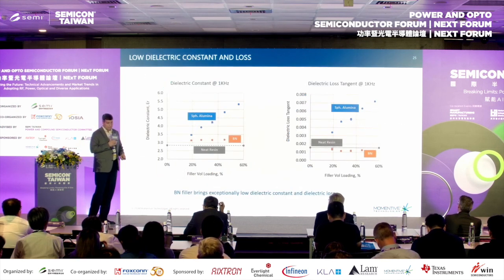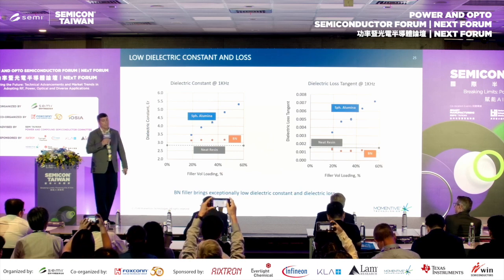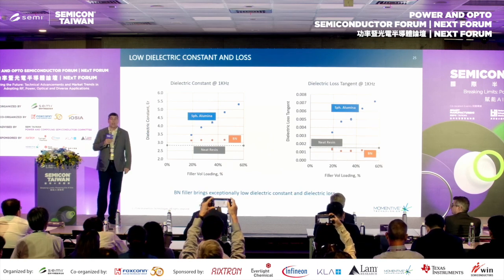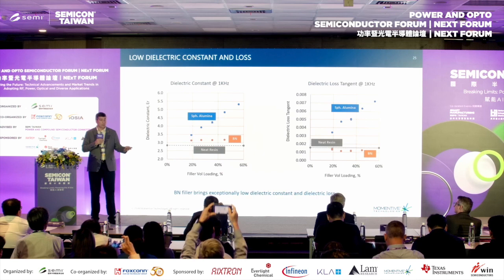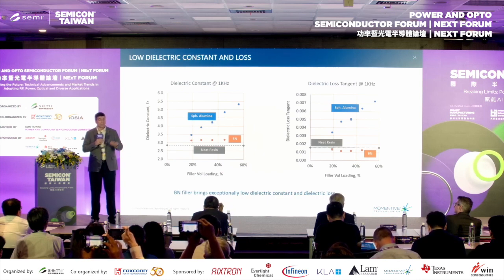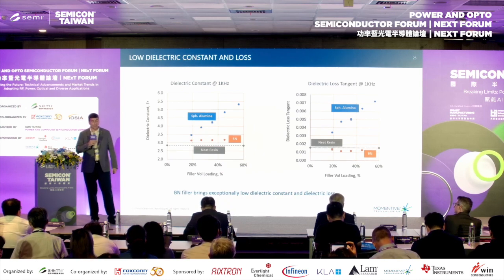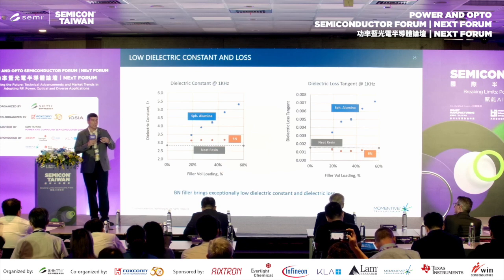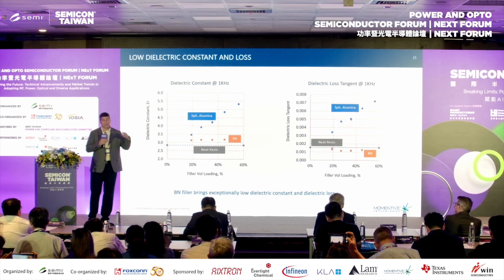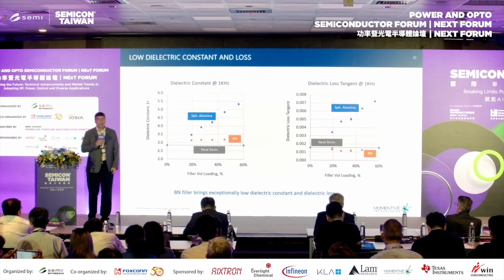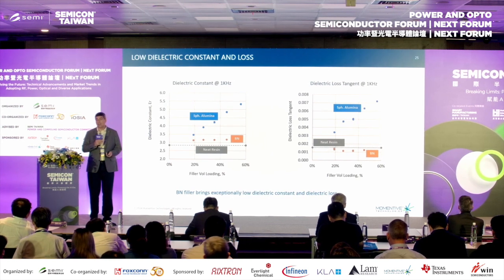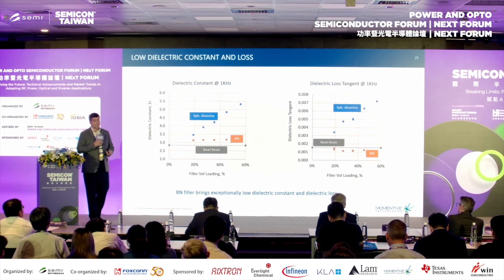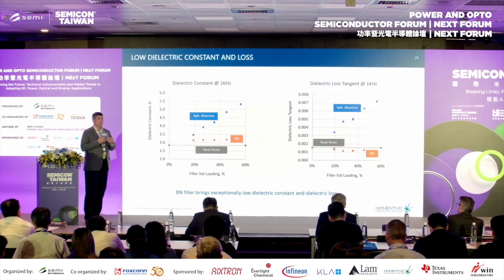And similarly, if you look at the dielectric losses that are associated with these different fillers, the BN versus the spherical alumina, again, all of this compared to the neat resin, you can see that the BN really has no impact on the material. So again, exceptionally low dielectric constant, dielectric loss. So again, if you're going to put this right in TIM1, at high frequencies, high voltages, these things matter.